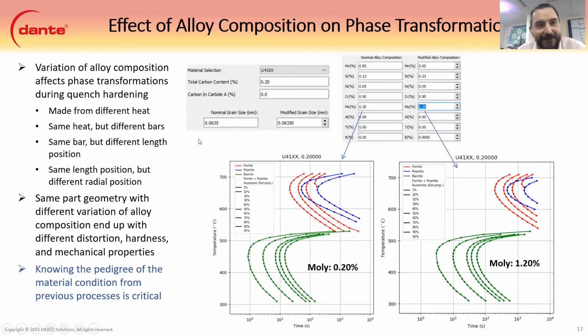So the variation of alloy composition is applied in here, and this slide shows the difference in changing a little bit of extra moly. Actually, it's a lot of extra moly in here, and how it shifts the diagram. You can see this is from 0.2% to 1.2%. Different heats and different bars will have different alloy composition, and we needed something to account for that. So we created this alloy composition algorithm inside the TTT diagram, so we can see the change in that.